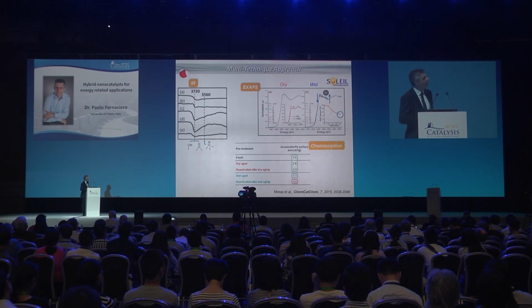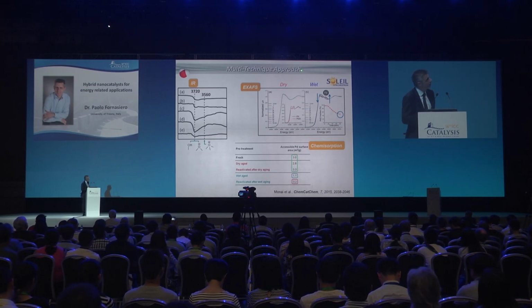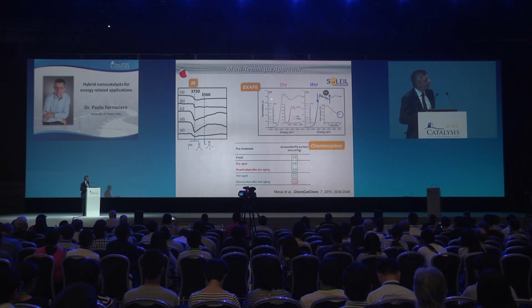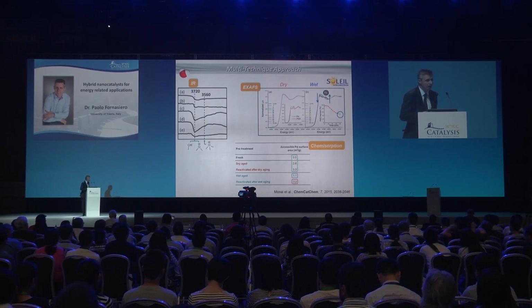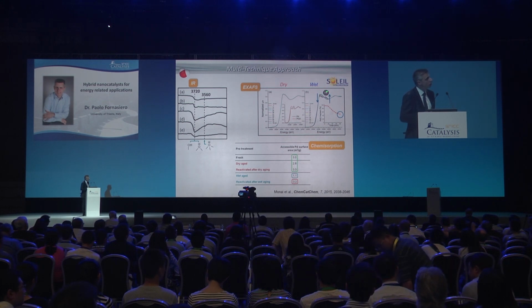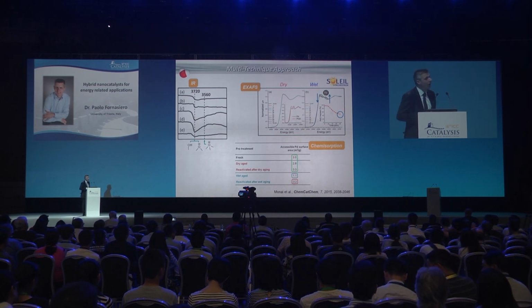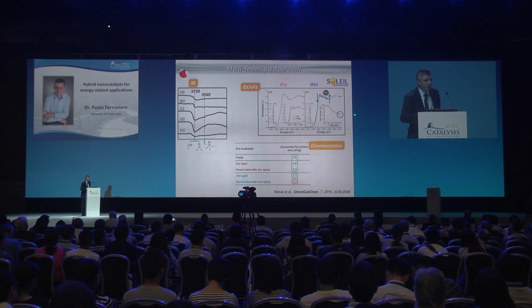Only operando XAS spectroscopy can tell us the reason for this deactivation. At high temperature, 600 degrees Celsius, under dry conditions, the catalyst is stable and methane is fully converted to CO2. The XANES spectra don't change with time and are fully consistent with palladium oxide, the active phase. Vice versa, in the presence of water, at high temperature and the same conditions, you see a change with time of the XANES spectra, and basically you transform palladium oxide to palladium metal, which is not active.